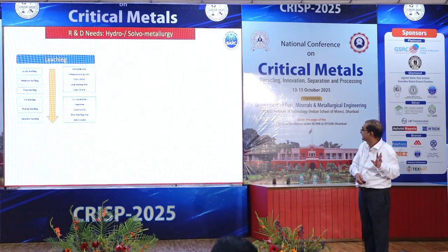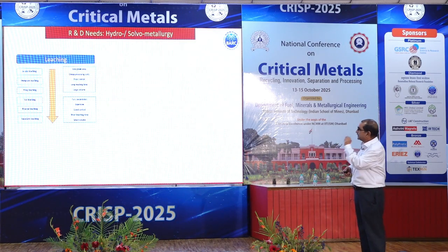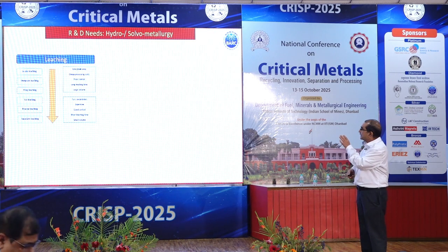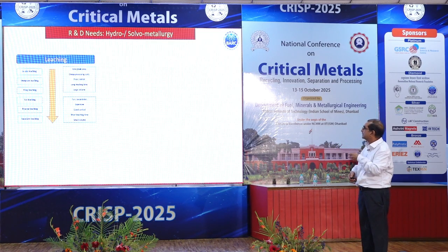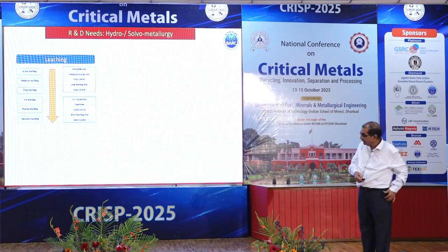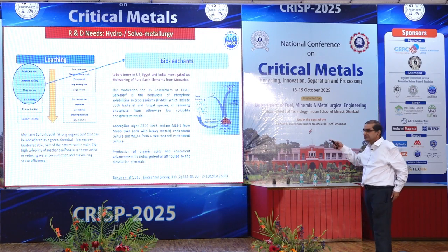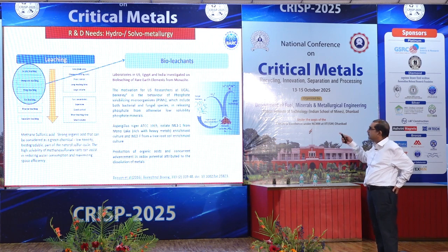Okay. Let us go to the specifics. Leaching, if you take, we have got some 6 types of leaching methodologies. One is in situ leaching, dump leaching, heap leaching, vat leaching, these things. There, a very important observation is, in all these things, we need to use bio-based leachants. And here also, we should not use whatever reagent we want. These critical minerals are known to be refractory. The bio-leachants which we are using conventionally may not be able to dissolve this.